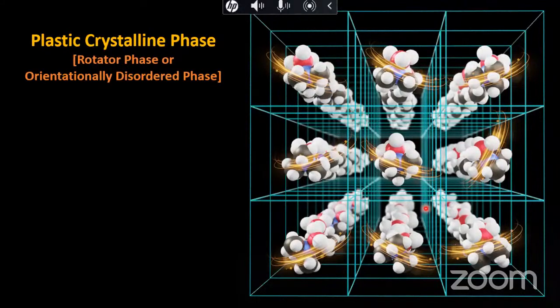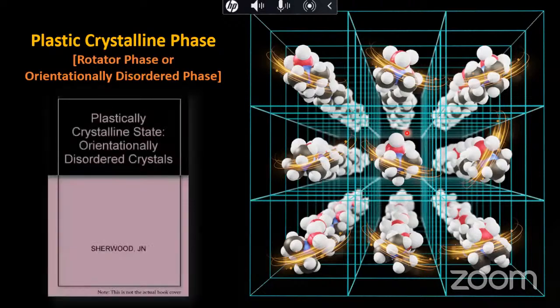If you diffract these crystals, you will see that there is a lot of disorder in these molecules. But the crystal itself is ordered, and you have long range order, and it is a solid, and diffracts very well, but molecules actually rotate. So these kinds of crystals are called plastic crystals or rotator phases or orientationally disordered phases. And so these have some unique properties. And there is a book you can look at if you want.